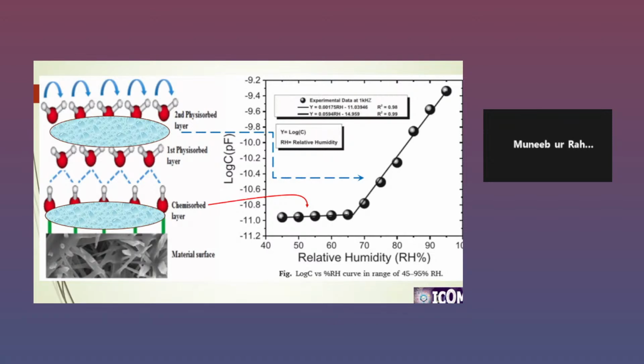So it is a less mobile layer. The H plus ion and OH ion cannot easily move from one electrode to another electrode. That is why the capacitance increase is not that pronounced. But above this, on the left side in the cartoon, above this first chemisorbed layer, the water molecules are just sitting on the surface of this chemisorbed water layer. So it interacts with the water molecules and adsorbs in a physisorbed fashion.